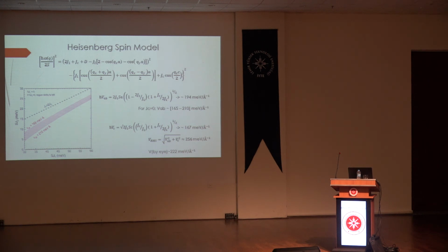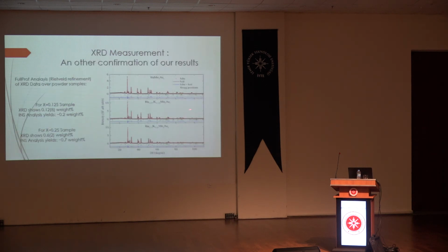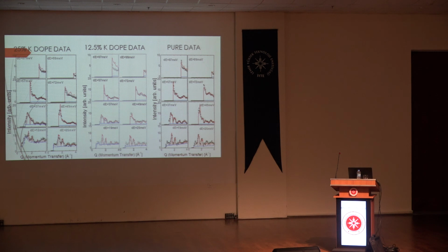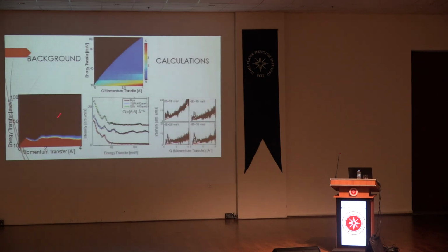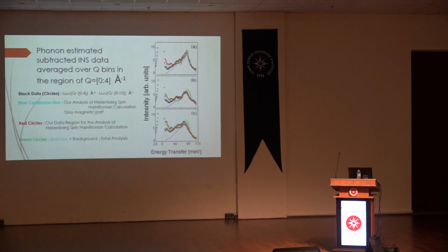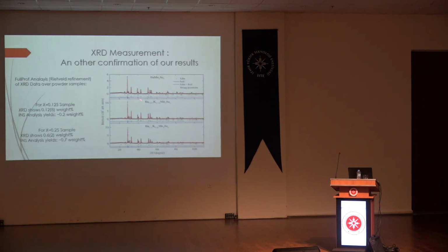Those equations were done by David Johnson. And I got very close to those numbers, as you see. And these are the numbers that are represented over there for J equals 0. And that is the confirmation of my talk. The unreacted manganese oxide was fit in my background here and scaled to there. And the scaling gives me exactly the same numbers as this magnetic X-ray diffraction analysis. This is done as the last point of my research.